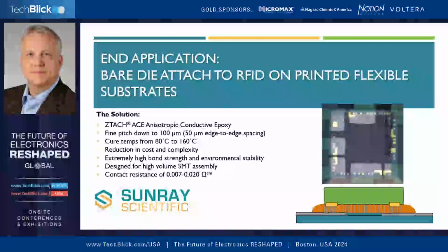So the solution that we proposed, or they came to us and asked us about, was trying ZTACH ACE. I'll talk a little bit about the technology on another slide for those of you who aren't familiar with the material. But that is our anisotropic conductive epoxy. We can manage pitch down to 100 microns with standard formulations. That would mean 100 microns center to center, center pad to center pad. So that's a 50 micron edge to edge. We can go finer than that. We can go down to a pitch of about 60 microns, which would be 30 micron spacing, depending on the formulation we use and the density of the components being populated.